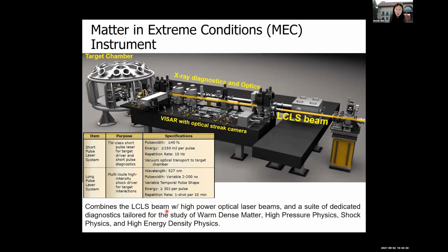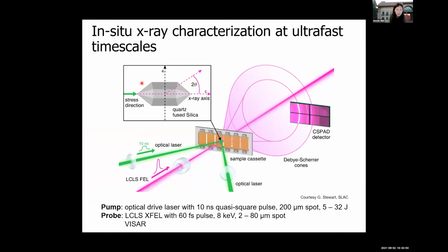So you can use the matter in extreme conditions instrument, MEC, to couple this very fast X-ray bunch with dynamic compression. You can generate a shock using optical lasers and then follow how properties are changing using the X-rays as the shock is propagating. So you can use ultra fast diffraction.